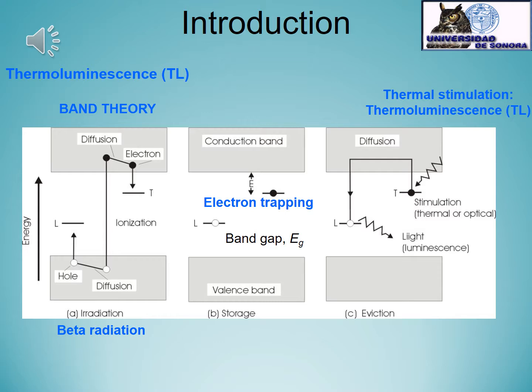When the electron goes to the conduction band, it can be trapped, which is the storage stage, in these trapping states, which are metastable states or energy states. Then we can have thermal stimulation, when the electrons are delivered from the trapping states and go to the recombination centers, which are color centers. This is the eviction stage.